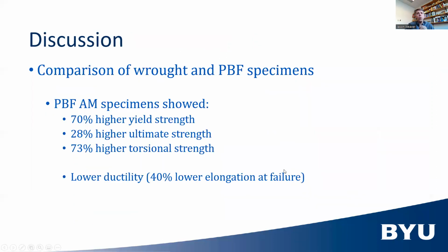So what does all that mean? Well, as we're comparing our original wrought material with our powder bed fusion material, we found that the PBF specimens had a higher yield strength, 70%, so quite significant, a higher ultimate strength, and a higher torsional strength, so higher strength overall. We did find that it had lower ductility, so it was more brittle. It had less elongation as it was being pulled.